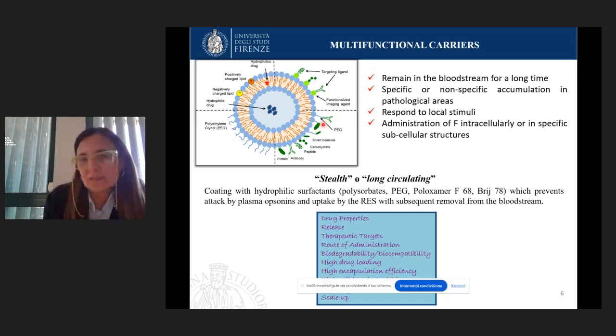In particular, we can in this way obtain targeting of the action of the drug by inserting on the surface particular ligands such as antibody, polyethylene glycol, carbohydrate, peptide, folic acid or transferrin, to target the action of the drug loaded inside the nanocarrier to particular cells, tissues, or organs. For example, if on the surface we introduce hydrophilic surfactants such as polysorbates, polyethylene glycol, poloxamer, and so on, it's possible to obtain stealth or long circulating nanocarriers to prolong the circulation time of the carrier and then of the drug.